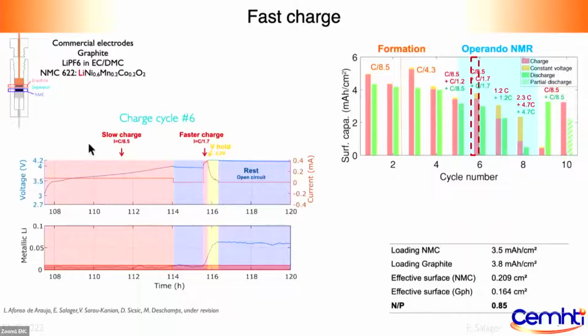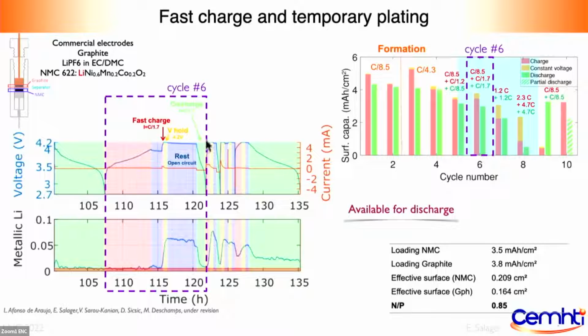And so what we could see is that, for example, if we go for a faster charge, so this is a current here given in portion of capacity and time. And so what we see is that if we charge very fast, we get some metallic lithium showing up. And then that's really during the constant voltage step that we get most of the lithium that is plated. And what was interesting here is that during an open circuit period, so you charge your battery, you disconnect it and you observe, then we saw that the lithium was actually not reacting. We could still detect it. And that's interesting because it can be retrieved as we discharge the battery.